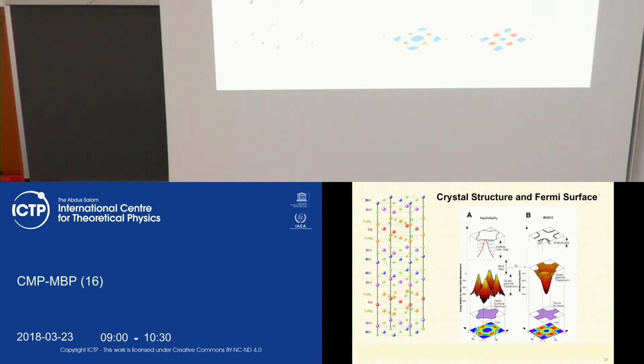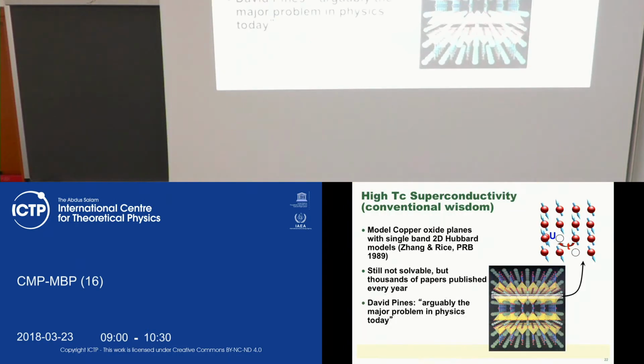This is yet another system, bismuth strontium oxide. See how complicated this system is. And having said that about this mechanism, people immediately start to think about Coulomb interaction, in particular the so-called Hubbard interaction, since the system at stoichiometric condition is localized, as I said, it's an insulator. Moreover, it was discovered that this insulator is an antiferromagnet, which was yet another indication that it has something to do with the Hubbard model, as we discussed in our previous lecture on Monday.